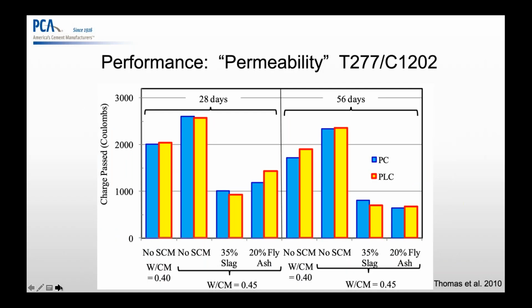As far as permeability, the chlorides under the ASTM C1202, Michael Thomas from the University of New Brunswick also did an enormous amount of research and concluded that whether it's without any SCMs or with SCMs, we can see an equivalent performance of the PLCs versus the OPCs.